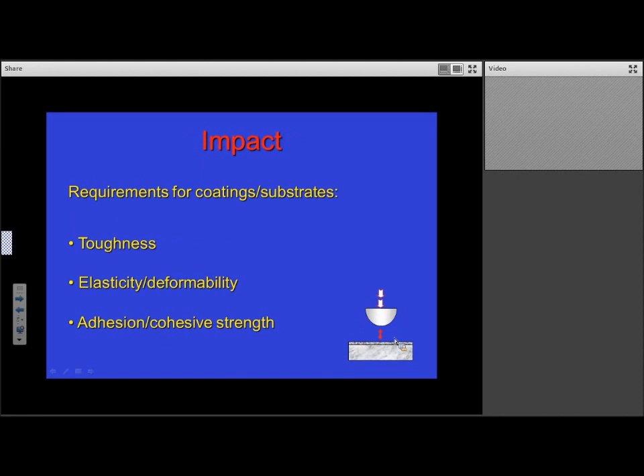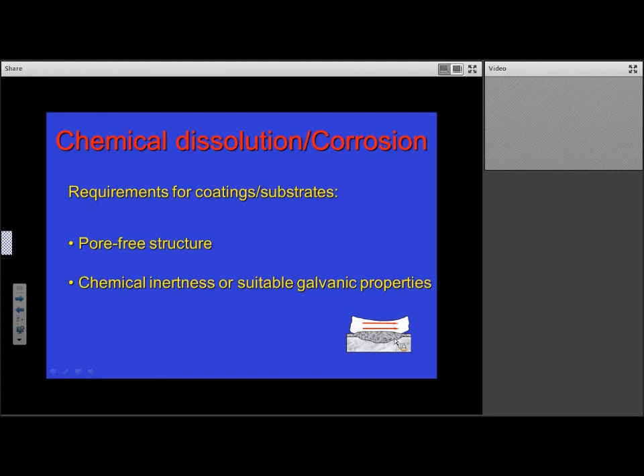Another of those types of contact which I illustrated was impact. Requirements for impact resistance are definitely toughness, ability to absorb energy. So you need elasticity and you need deformability, you need good adhesion of the coating to the substrate, and you need cohesive strength both within the coating and within the substrate. And then the final schematic that I showed was when you have chemical dissolution or corrosion. In that situation, you'd ideally like to have a pore-free structure, and you're going to need either a completely chemically inert barrier, or you're going to need some suitable galvanic properties within the coating. So again, we saw that many of these nanocomposite coatings give a dense, relatively pore-free structure.